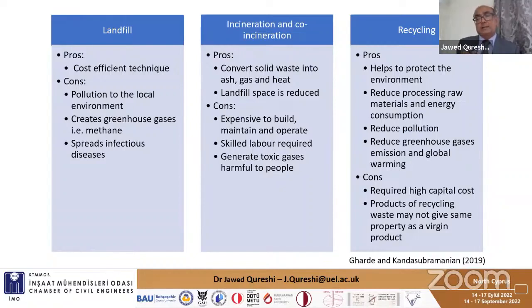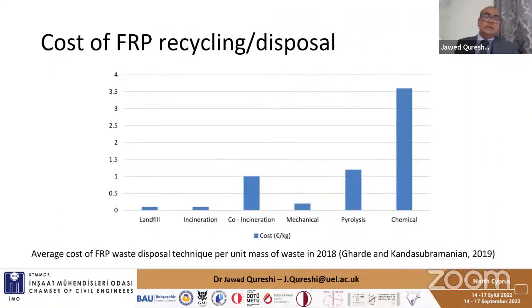Some processes are not commercially viable. Chemical and thermal recycling can only be used at a very small scale; for larger scale applications, mechanical recycling is used. In the cost analysis, landfill is the cheapest disposal option, though space may be limited and regulations strict — particularly in Europe. Of the recycling processes, mechanical recycling is the cheapest. Pyrolysis is a type of thermal recycling. Chemical recycling costs significantly more, so it is only economically justified when the fiber value is very high, such as with carbon fibers.